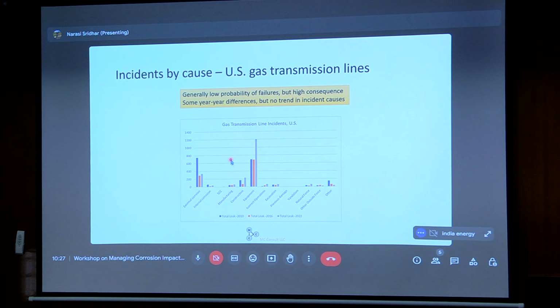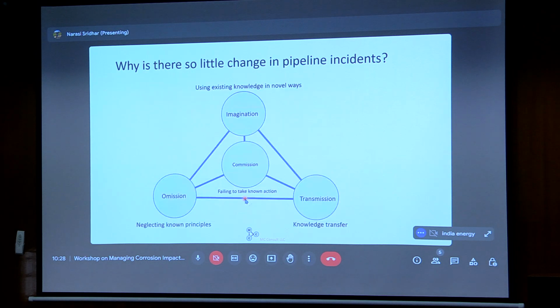This is incidents by cause, and you can see external corrosion. This is three different time periods, 2010, 2016, and 2022. And you can see that external corrosion is one of the bigger contributors. Bad specification or operation of equipment is another major contributor to failures. Stress corrosion cracking is down in the weeds, although some of the stress corrosion cracking incidents have led to major failures.